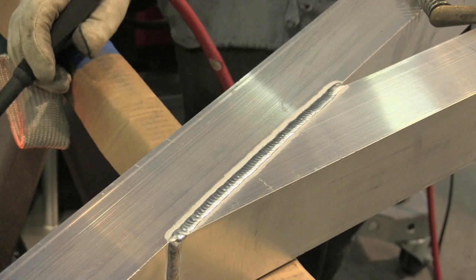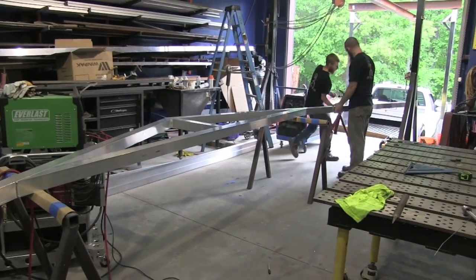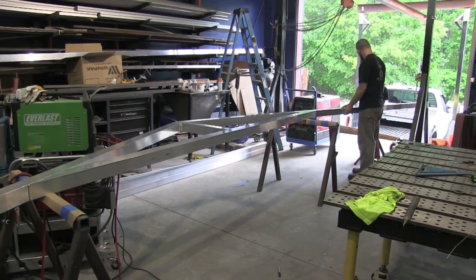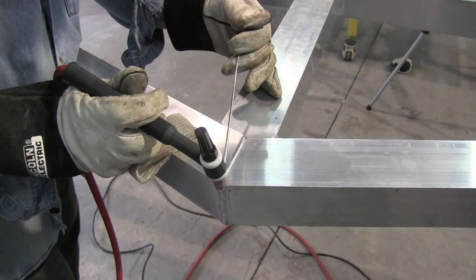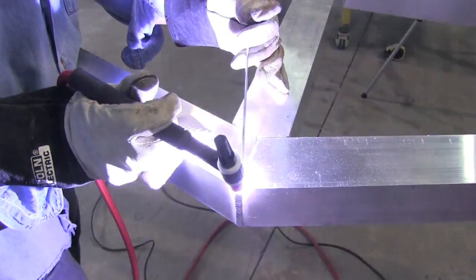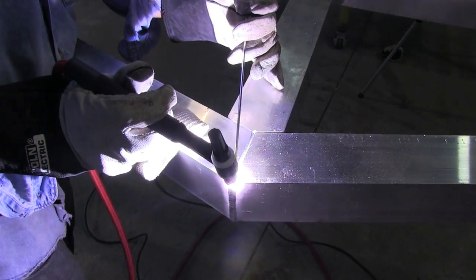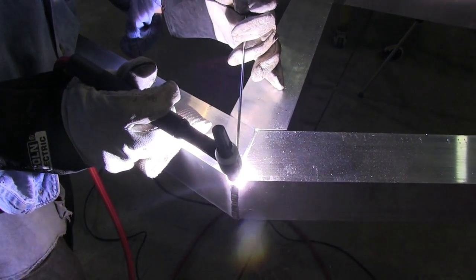Again full pedal, 200 amps. Trying to just motor out as quick as I could, at 200 amps anyway. I actually could have gone a little faster if I had a few more amps, but that's about right for travel speed. Using a 1/8 to 3/32 diameter filler metal here.